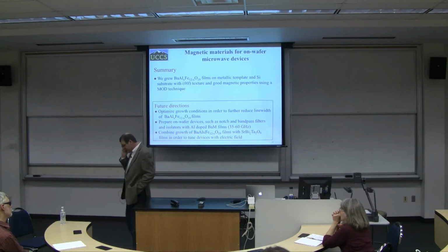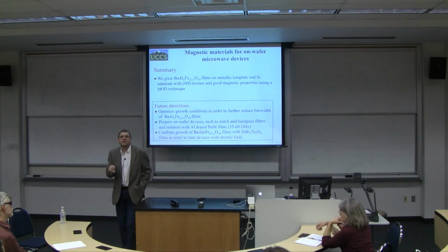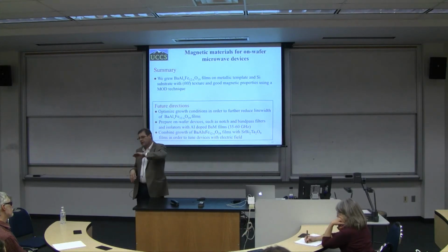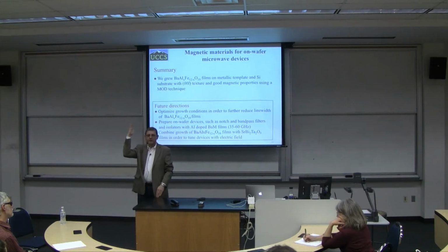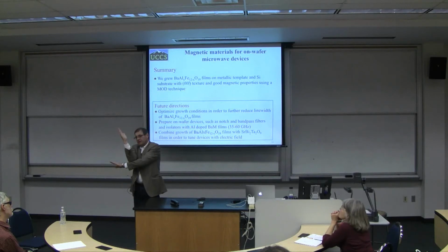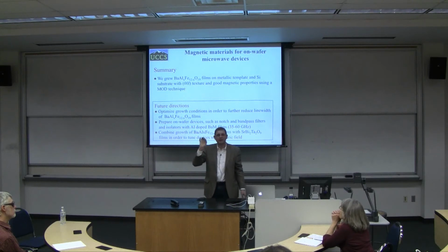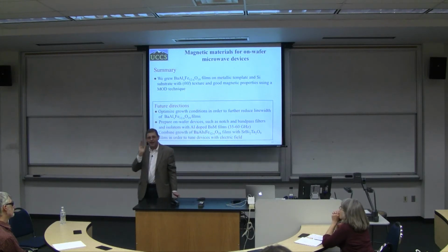in the Kerr effect is basically change of polarization of the light. So imagine the following scenario: this is the electric field of my light which comes in. And I have here magnetization pointing in this direction. And so what's going to happen is when the light passes through the material with magnetization pointing in this direction, the light plane of polarization is going to slightly rotate. These changes are very minute. We are talking about a fraction of a degree, okay?